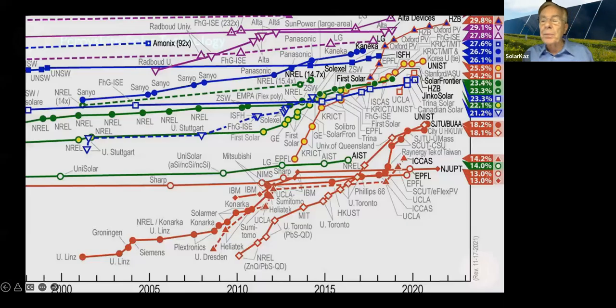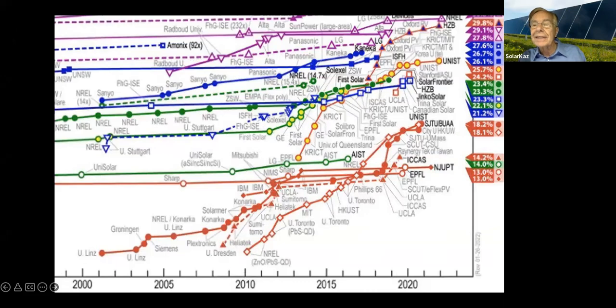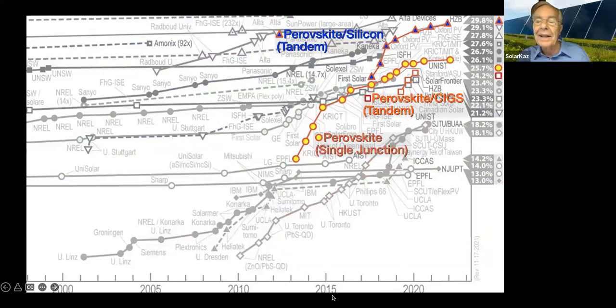So let's look at this perovskite technology. And if you look at this thing and follow-ups on this whole thing, you can see that since about 2013, these things were introduced and now have reached ranges of, for single junction perovskites, that are about 25%, but more, these tandems that they grow the perovskites on top of silicon have reached nearly 30%, okay, on research cells on this whole thing. So this is why a lot of the interest is turning to this. You're getting very, very high efficiencies, either from single junction devices, but even for tandems, whether it's on silicon or some other materials, to get things that are nearly 30% efficient on this.